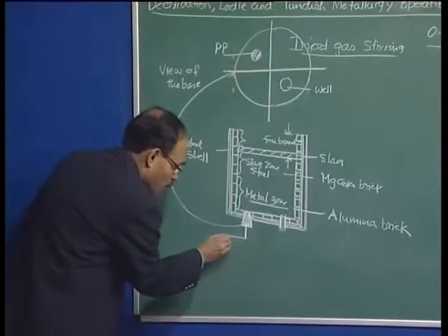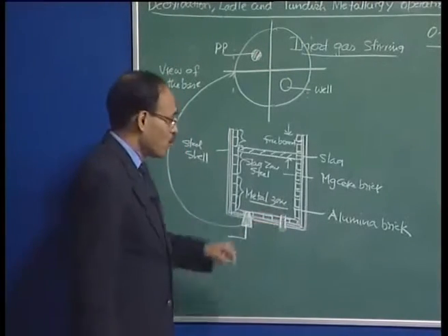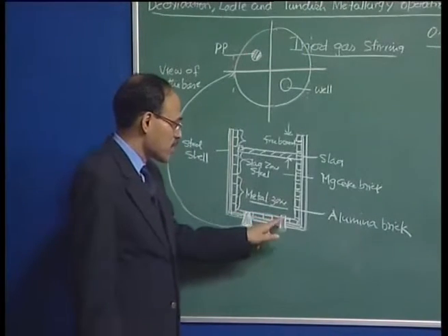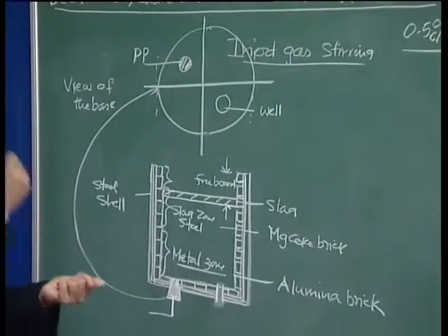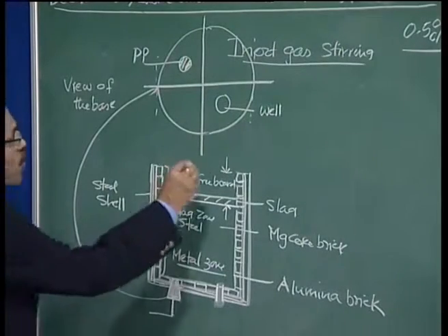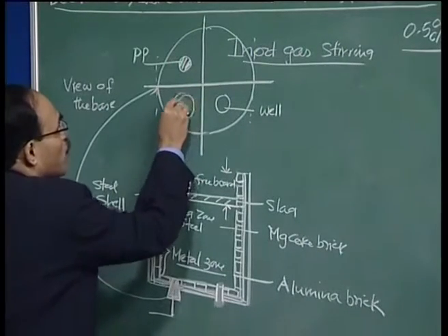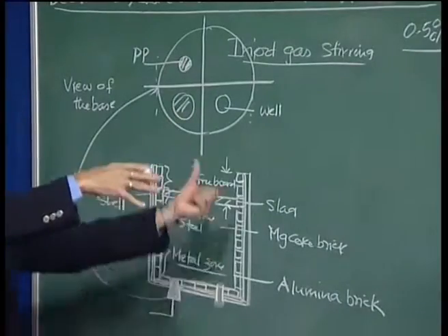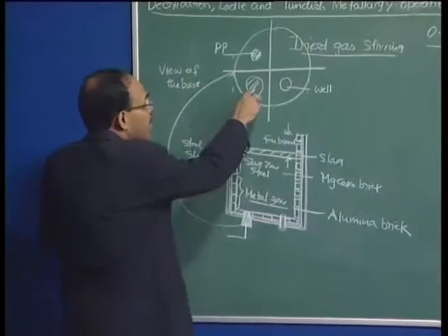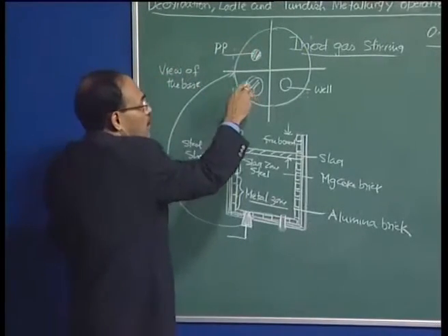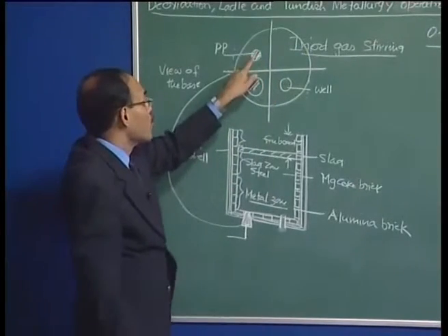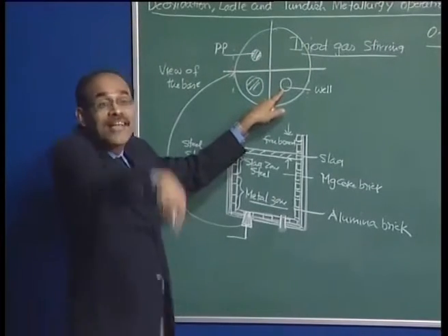So through this porous plug, as we introduce gas, it is through this well we are going to be taking out molten metal. Typically during the process, this remains closed by using some refractory or ramming material. And somewhere here we must understand, this is the region you should plan, that when the molten steel stream from the furnace enters the ladle, it is here that the stream really impinges. If the steel impinges here or here, there is going to be significant damage to the ladle. We don't want the porous plug or the well region to come directly under the falling stream.